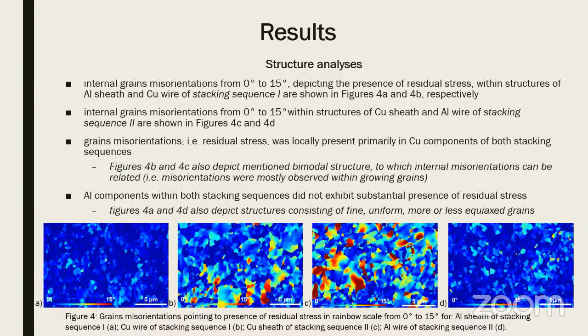For both the aluminum components, so the stacking sequence 1 aluminum sheath and the aluminum wire of stacking sequence 2, we see that both the structures consisted of fine, more or less equiaxed grains, and the presence of residual stress or internal grain misorientation was not so significant for these components.